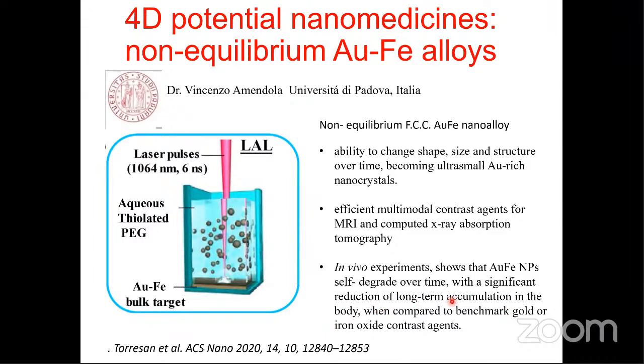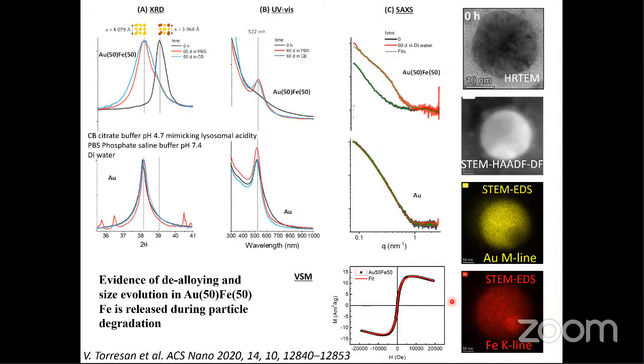Here we have the iron-gold nanoparticle, and we see that when the nanoparticle is kept in citrate buffer, mimicking lysosomal acidity, the position of the peak changes. Also in phosphate buffer at pH 7.4, the position of the peak changes to a position that is coincident with gold nanoparticles. If we look at the starting gold-iron nanoparticle, we don't have the plasmon, but after aging, we start having the plasmon. And in small-angle scattering, we see a huge change also in the alloy.